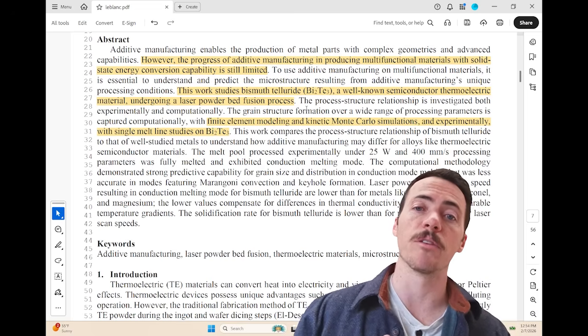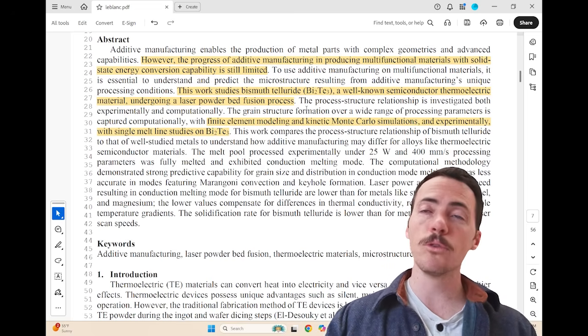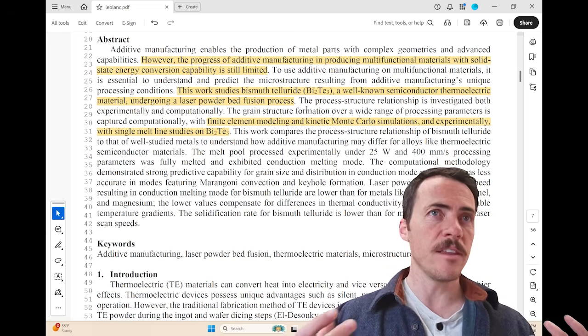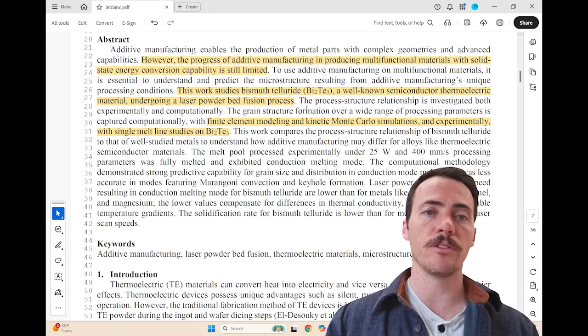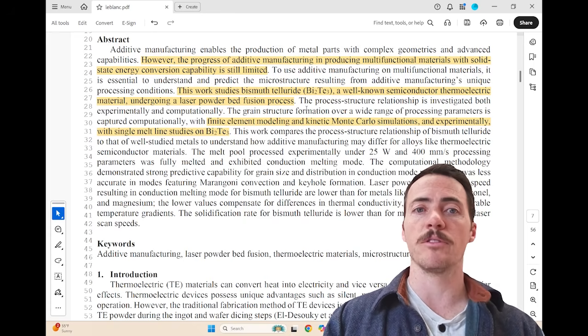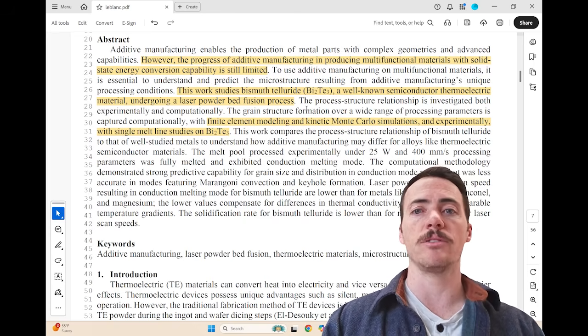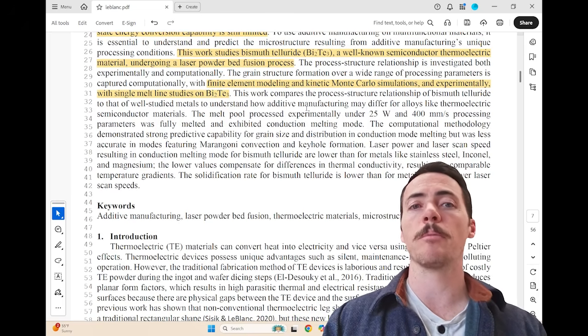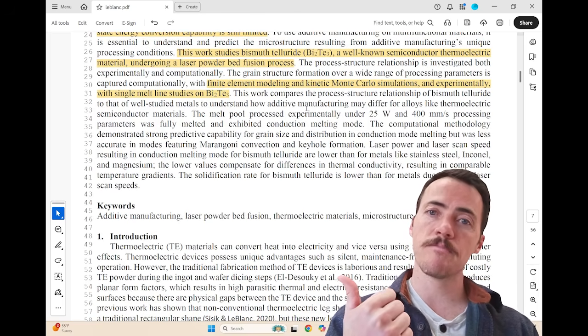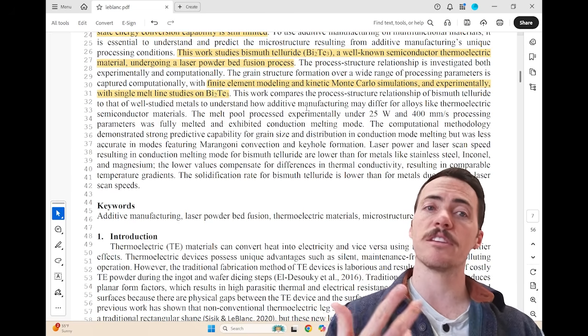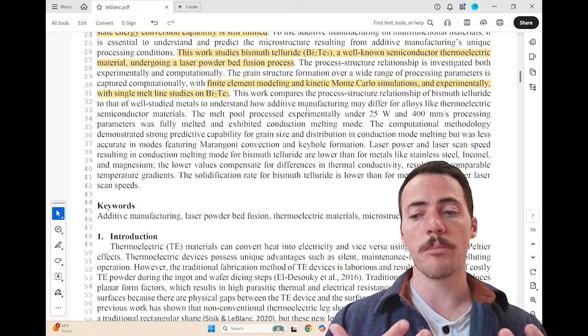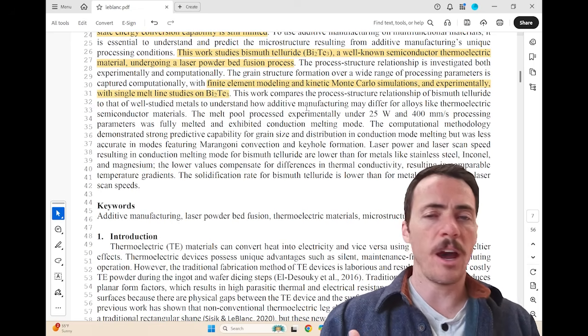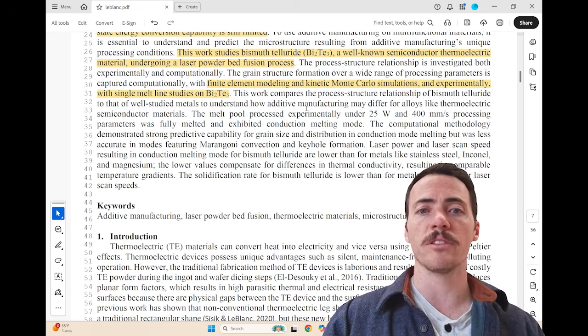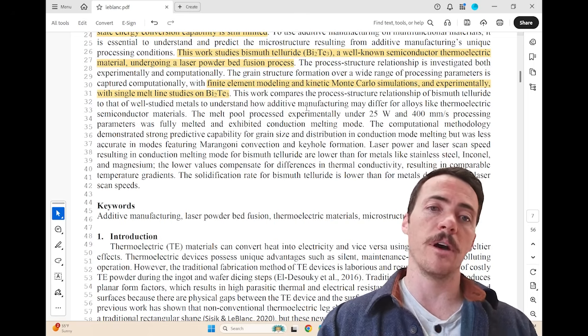My background is in thermoelectrics, and we're seeing this all over the place. And if you could print these materials, I could see that being a real advantage. So knowing how to additively manufacture the material would be great, but has some challenges. And they're going to address it in this paper by combining finite element modeling, kinetic Monte Carlo simulations, and experiments to figure out the right processing windows and to understand how exactly does this functional material process and behave differently than it might with a metal.